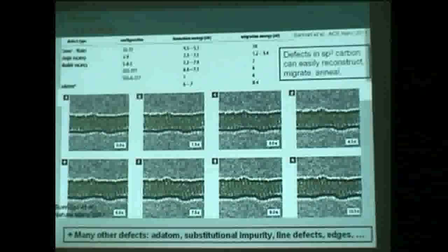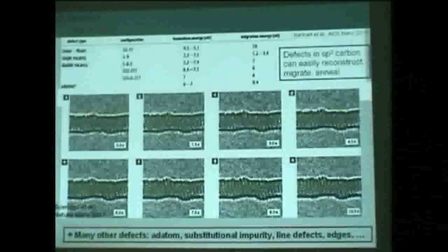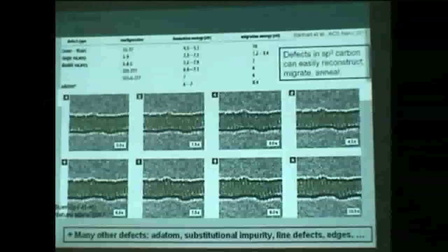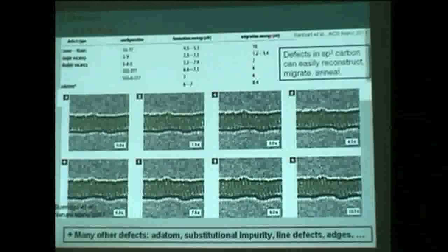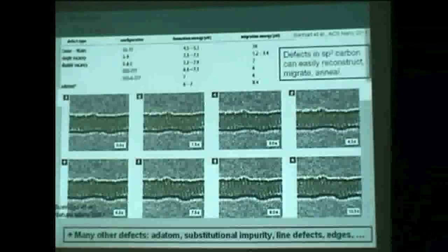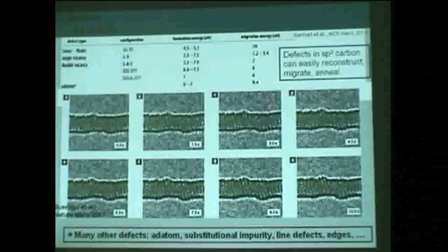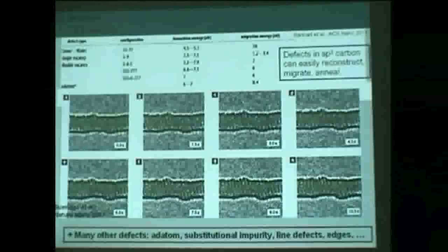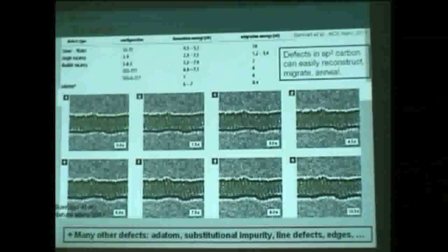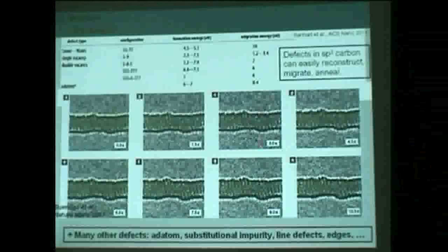At some point, these defects can meet. In some conditions, they can even anneal each other to create something which is more stable and more crystalline. And this is possible according to calculations, because the migration energies in this graphene lattice, in this carbon lattice, are quite low. It's several eVs, a few eVs, so it means that it's actually possible for these defects to go over this activation barrier and to move, to diffuse, to migrate in the graphene lattice. So here this is in the case of a nanotube.